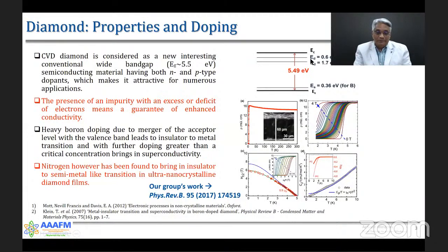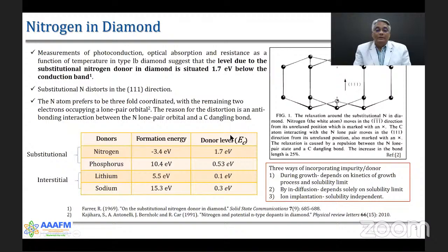because as you can see here, the donor levels are deep inside the forbidden gap. The nitrogen donor level sits 1.7 electron volts below the conduction band. Nitrogen and phosphorus make good substitutional impurities. Lithium and sodium go into interstitial sites. There are three ways in which impurities can be incorporated into the diamond lattice.